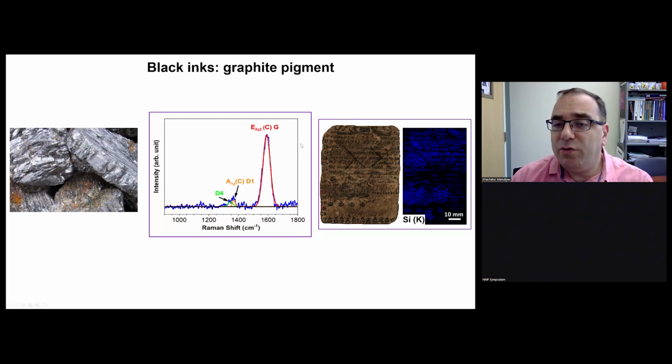But if you run this spectroscopy on carbon lamp black, you will see a different pattern. Most likely he used natural graphite, because we also find some impurities in the graphite, which is characteristic of naturally occurring graphite, to print this money. We don't see this type of printing ink colorant in any of his other printing jobs, including the Gazette. So this was unique, and somehow he managed to print with this graphite.